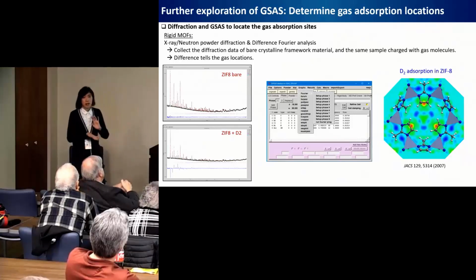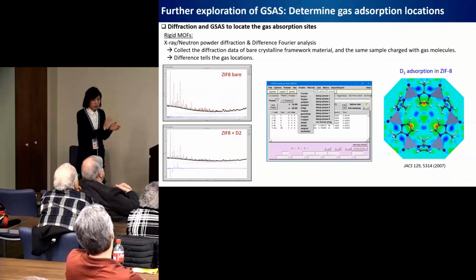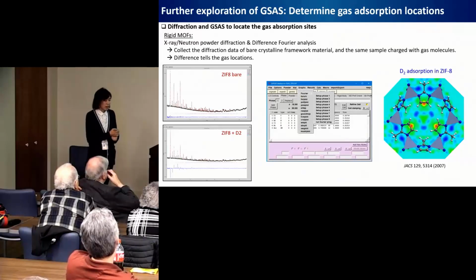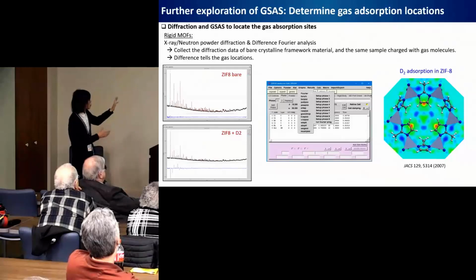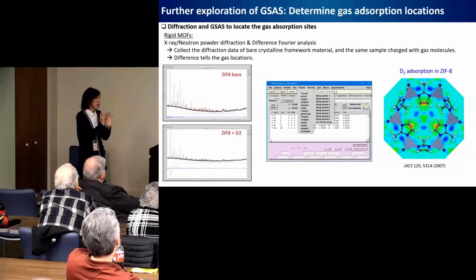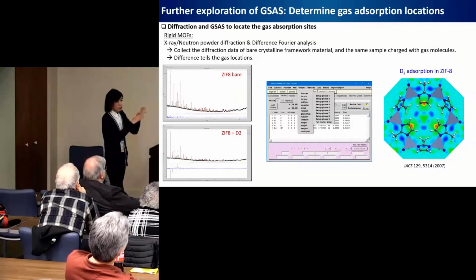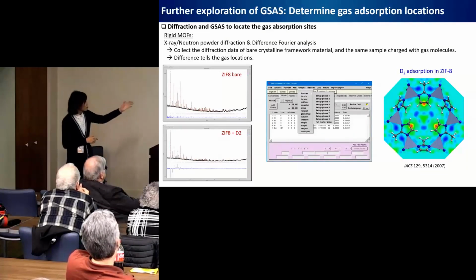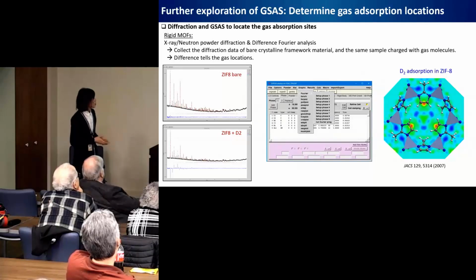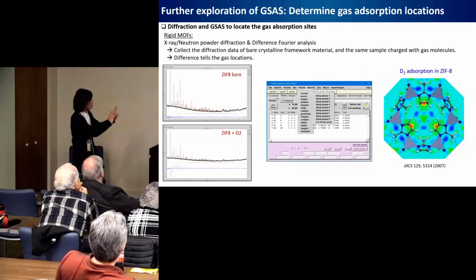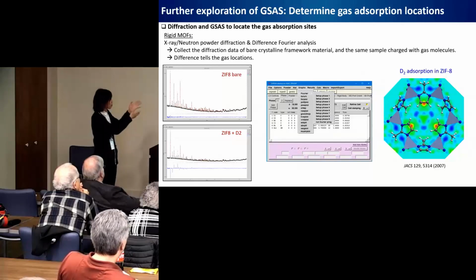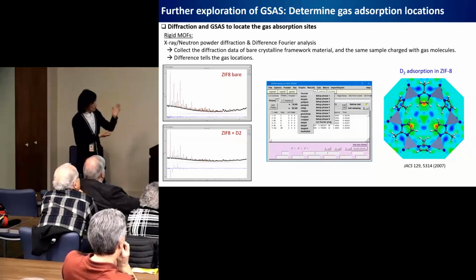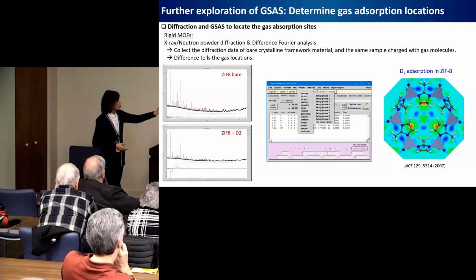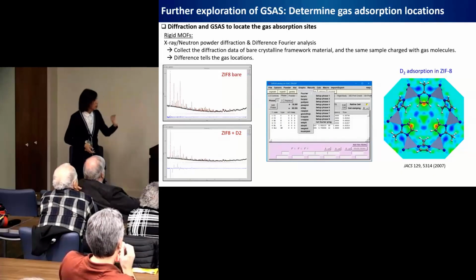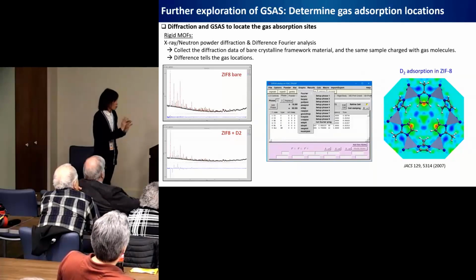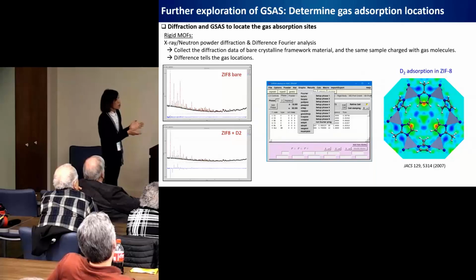So we usually collect a pair of diffraction patterns. Pattern 1 is from the empty framework, and then we charge the framework with the gas we are interested in. Because for a rigid framework, the structure will not change upon gas absorption, we just compare the scattering difference of the peak intensities. And GSAS provides this wonderful function for Fourier difference analysis. It will do the Fourier difference analysis and export the Fourier difference map. And then we can superimpose the structure on top of the map, and the highlighted scattering difference will indicate the possible absorption site for gas molecules.